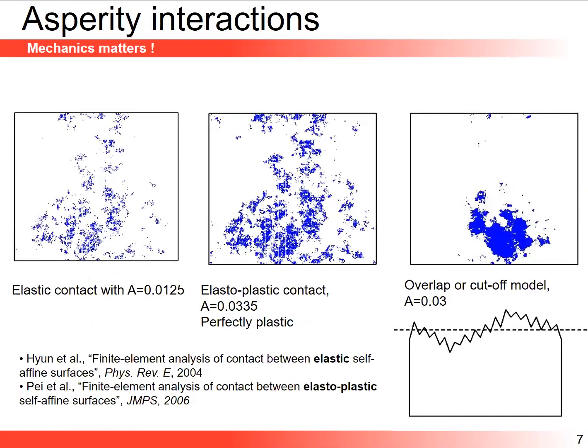Okay, so another take-home message in this general introduction that I want to bring to you is that mechanics matters. And I will go back to this point at the end of my talk. There are asperity interactions. So these figures are taken from old papers from 15 years ago from my first student, Lin Pei at Johns Hopkins, where we compared finite element simulation results to what used to be, and still is to some extent, a standard model in the tribology community, which is called the overlap or cutoff model. So on the right, this right image. The overlap or cutoff model is a purely geometric model. Surfaces are rough, okay? So here you have a schematic of some surface roughness, and you have this dashed line, and you consider that what is above the dashed line is in contact, and what is below is not contacting. So, a purely geometric model.